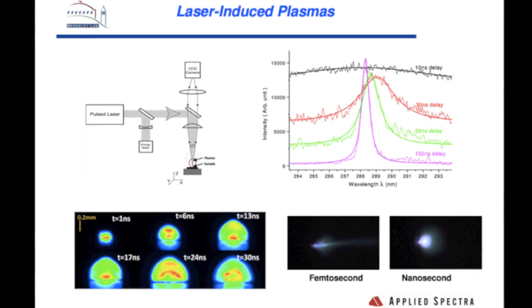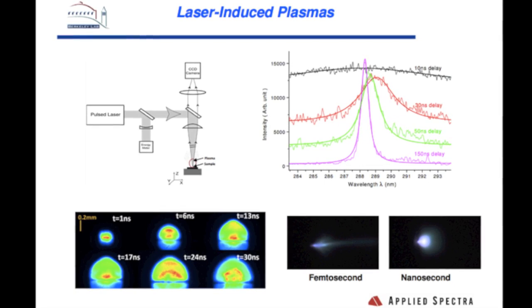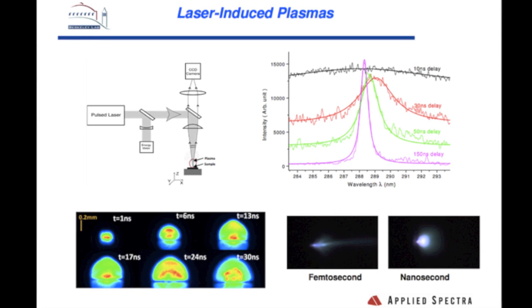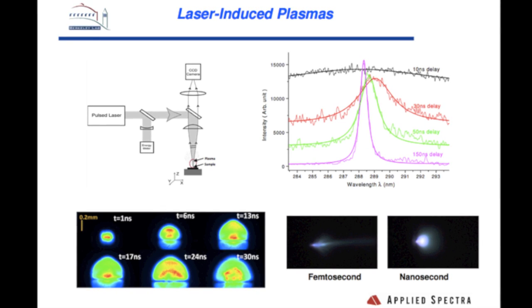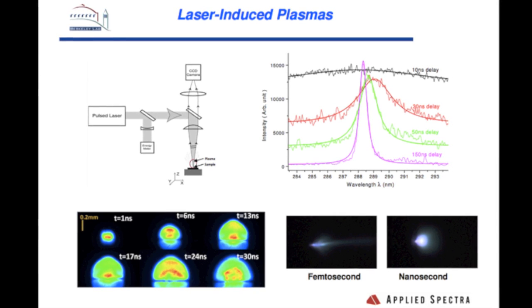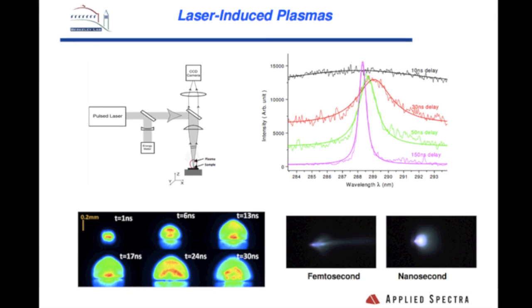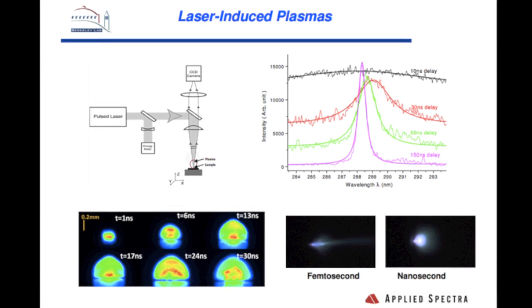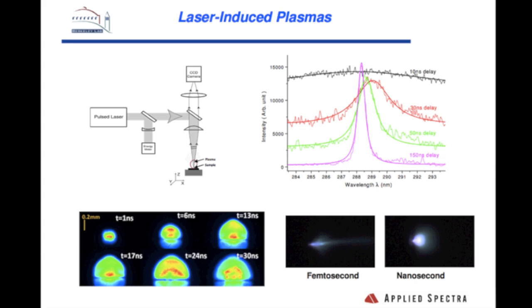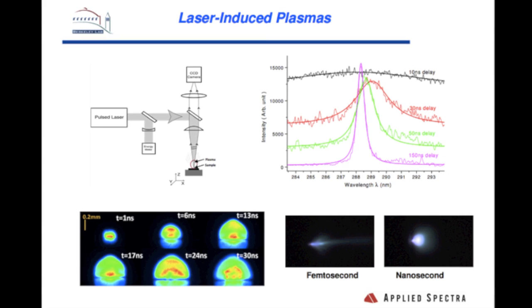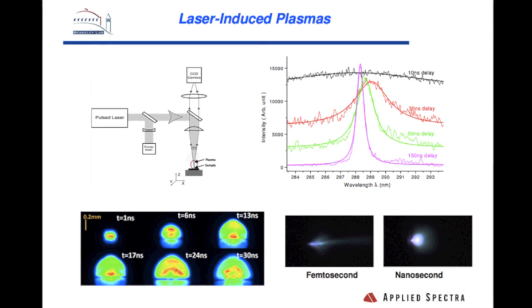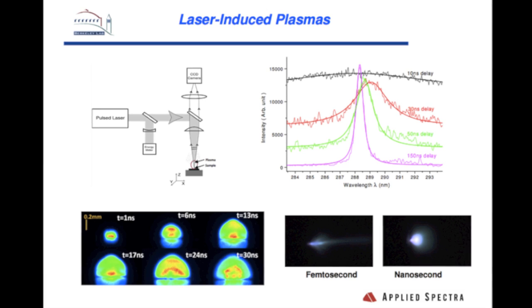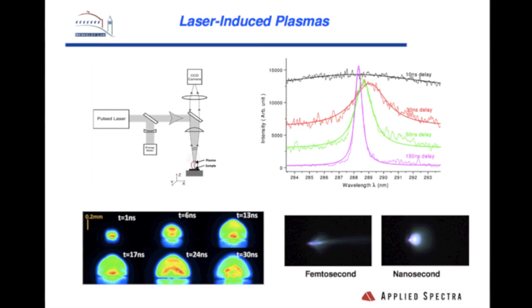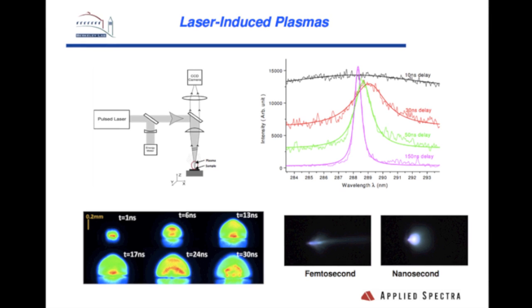So the laser-induced plasma, or LIBS, laser-induced breakdown spectroscopy, we're mostly going to concentrate on that in this talk. I'm going to talk about doing analytical chemistry with the plasma, not by collecting the particles. If you collect the particles and go into an ICP-MS, then you can do a lot higher sensitivity because most of the mass that comes off from the ablation is particles. A lot of energy does not go into exciting that plasma. It goes into the formation of plasmas or this spallation process.